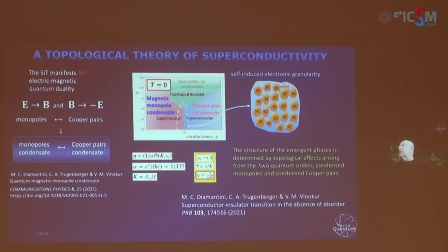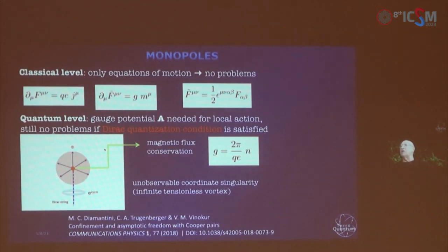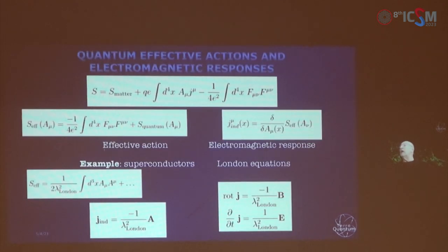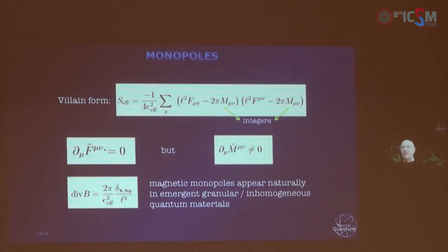And this granular structure is defined by topological effects arising from the presence of two quantum orders, condensed monopoles and condensed Cooper pairs. Okay, I just briefly remind you where these monopoles appear, because as soon as we try to establish the full duality between electric and magnetic phenomena, it works pretty well in, let's say, vacuum, but it doesn't work in condensed matter unless we introduce magnetic elementary particles, monopoles. Actually, Paul Dirac was first to introduce them, so we call them Dirac monopoles now. And then we can construct the action describing these monopoles and see that indeed all the physics of superconductors can be very well described in the framework of this model. So it's just a brief summary of what we can do.